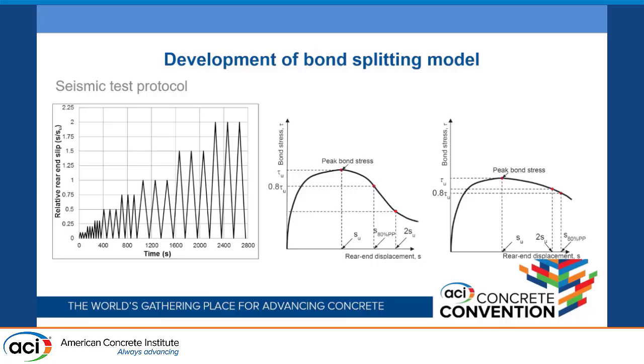So we said, let's say we have a rebar which is failing in a brittle failure mode, and in the other case it can have a ductile failure mode. So we said, let's define two displacement limits. One is when the load drops down to 80% of the peak load, and the second is 2 times the SU, where SU is the displacement at peak load. And we say take the higher of these two, that means the higher of either 2 SU or 80% of the post-peak load. That is our final limit of displacement until where we will do the cycling.